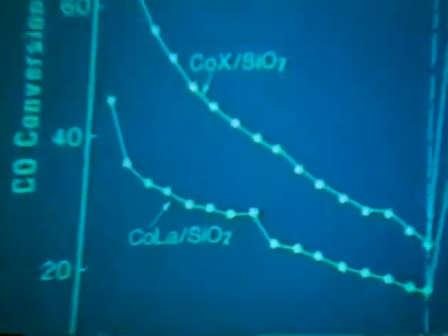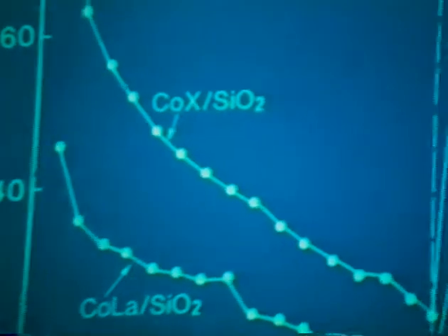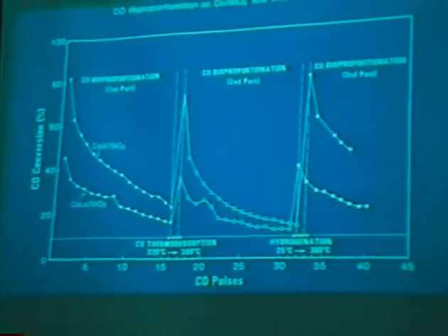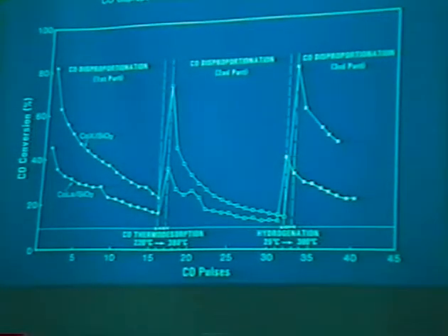Since the first step of the Fischer-Tropsch synthesis is CO dissociation leading to carbenes, we looked at the CO disproportionation experiment as a model experiment to try and classify the facility for different cobalt-based formulations, or the catalytic formulations I just presented, to favor the chain growth towards higher alcohols or higher hydrocarbons.